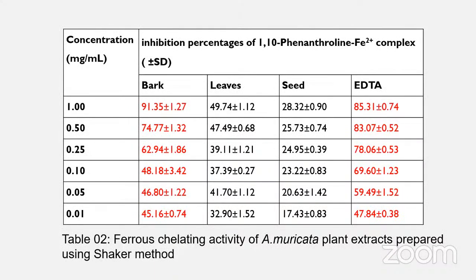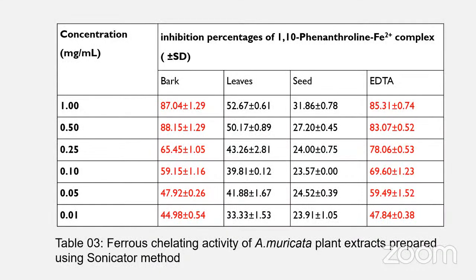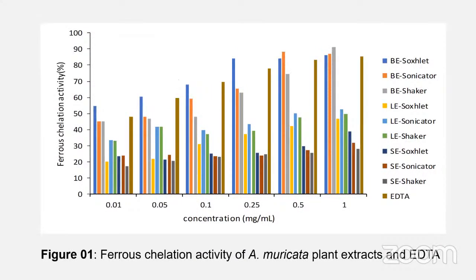Similarly, this table shows the ferrous chelating activity of the extract prepared using the shake extraction method. According to the results, bark has shown promising activity and others have shown weak activity. This table shows the ferrous chelating activity of Annona muricata plant extract prepared using the sonicate extraction method; as before, the bark has shown promising activity. All results obtained in the study are summarized in this graph.